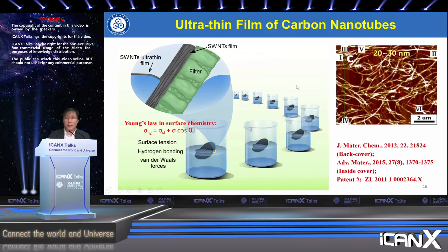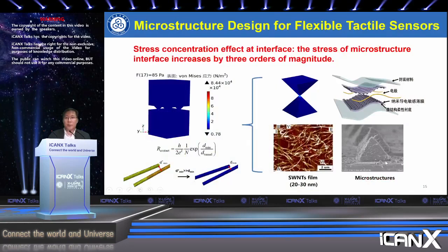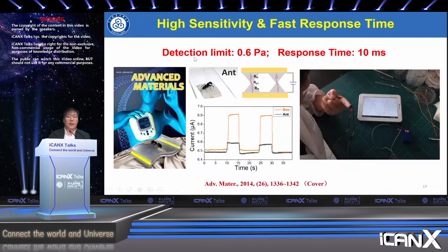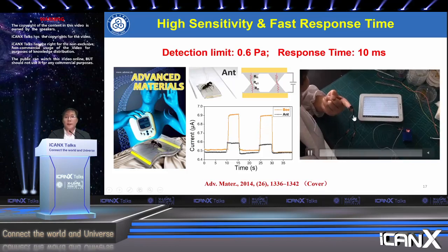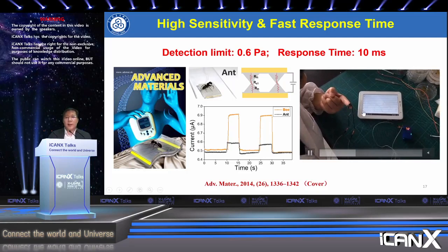So we cover this carbon nanotube network with these pyramid structures, and we assemble them as double-layered piezoresistive devices, so we can get a very high sensitivity to pressure. For example, we put an ant on these devices, so we can get a very fast and sensitive detection of the weight and the pressure. And for this material, we just put it on our fingers. So you can see here that it can monitor your heart rate in real time.